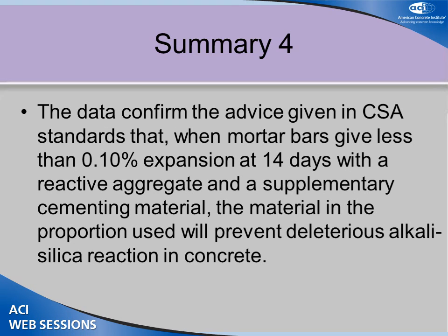The data confirms the advice in the Canadian standard that when the mortar bars give less than 0.1 in the ASTM C1567 mortar bar test using SCMs, that seems to be sufficient, with this particular aggregate, certainly to mitigate it. So it confirms that advice that we put in a long time ago, and now we have this longer-term data.